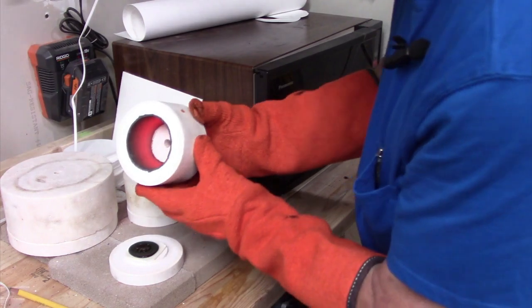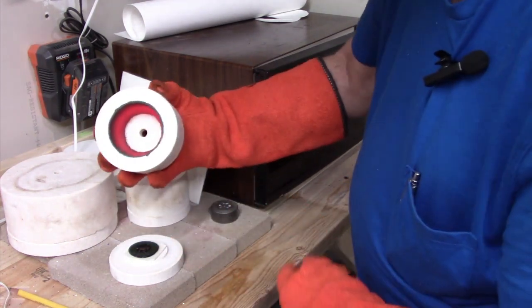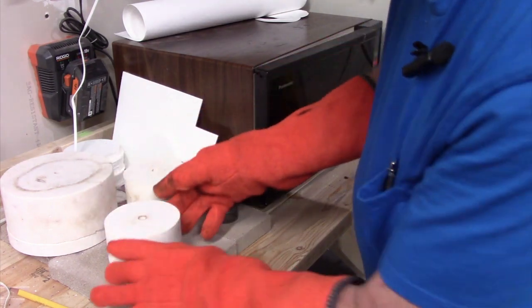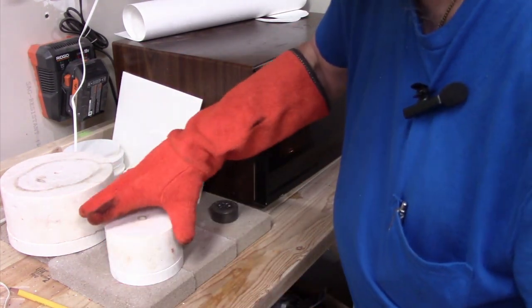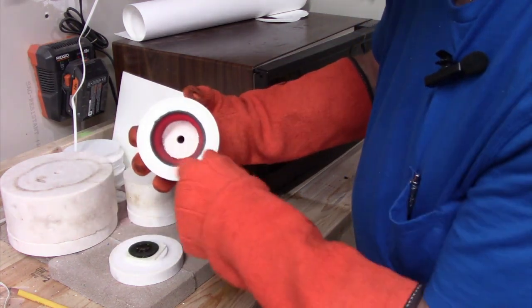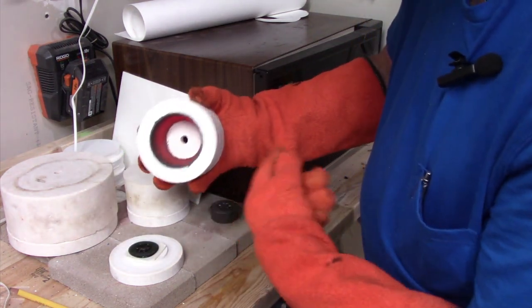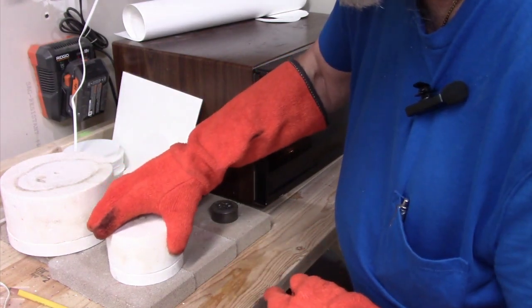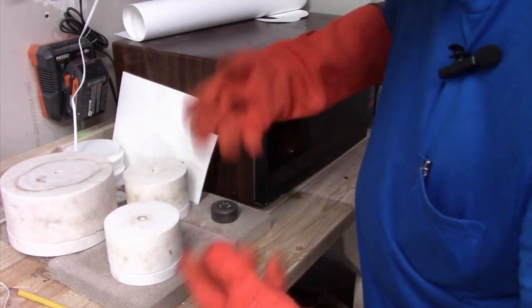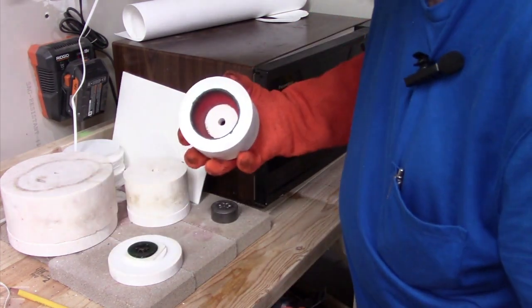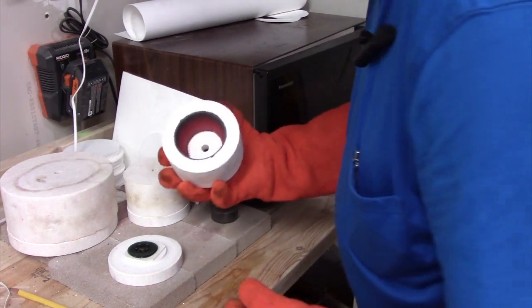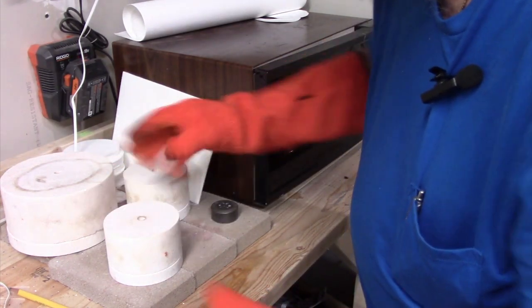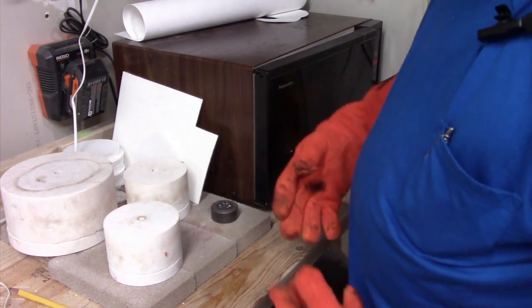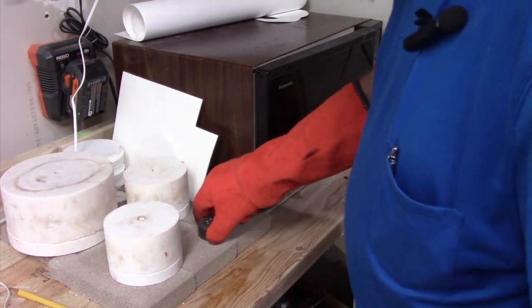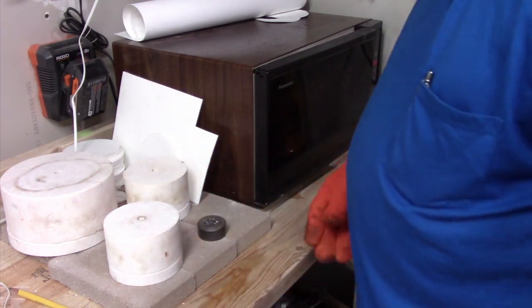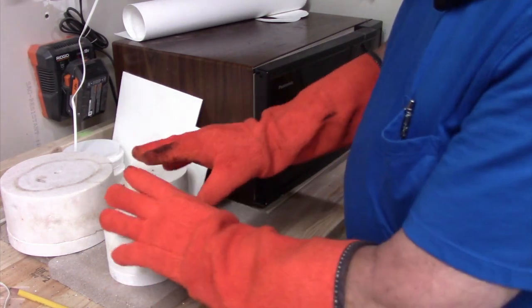and then if you need to, I often blow on this lid. I like it to be about 1/3 red, orange. And I've discovered that in my hands, when I use my high temp thermometer for the kiln, that will stay about 950 to 1,000. As long as it's below like 1,100 degrees, you're not going to re-melt the glass. And that's what you want to avoid. You want to avoid both re-melting the glass, but you also want to avoid letting the glass become too cool too quickly. So now what I'm going to do is leave this sit for an hour or two at least, and that'll cool it naturally.